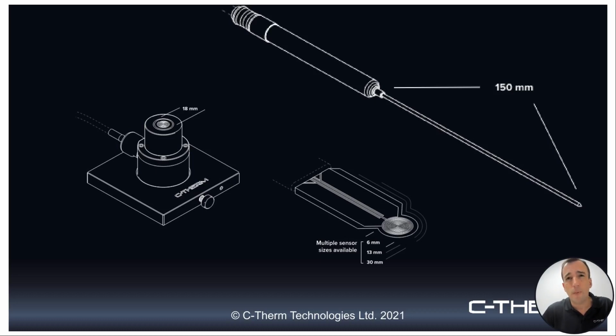The sensor we'll probably talk about the least today is the needle probe, transient line source. This is a sensor that's used for very sticky situations quite often. So think like polymer melts, anything that might bond to the other sensors and damage them in trying to remove a bonded material. Well, this is where the stainless steel sheathed needle probe is an excellent complement to our other sensors. And you can see it's quite a bit longer, so it requires quite a little bit larger volume of material.